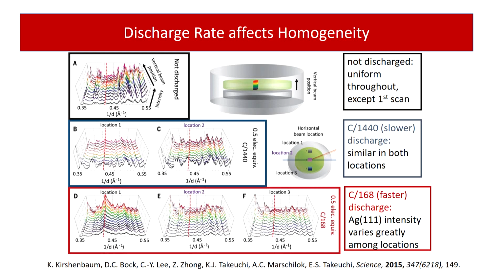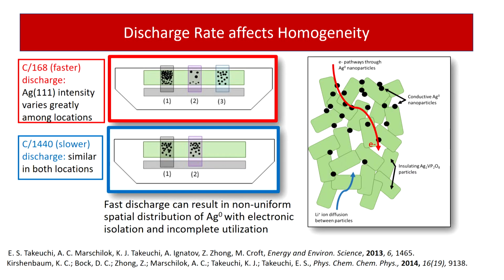EDXRD has been extremely useful here. We can map where the silver forms. We can map the silver network. Silver is a heavy atom, and we readily see this through diffraction. And what we find is that the formation and the homogeneity of the silver network is rate dependent. If you set up the network first at low rate, you get very uniform formation of silver metal. If you try to discharge it really fast initially, the silver metal forms like highways through the cathode, and it's not as uniformly distributed. That's kind of illustrated here. Slower is more uniform.